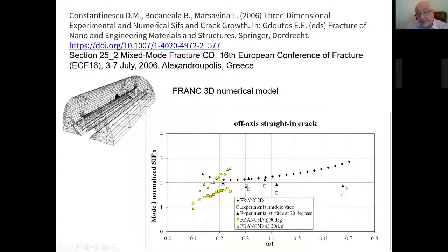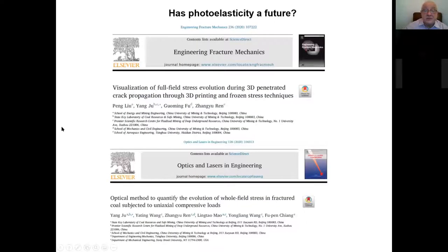Experimental results show that what is at the surface from the point of view of normalized stress intensity factor is a little bit greater than in the middle, and it slightly decreases, as I have mentioned previously, if the crack is grown more. We had this extreme experimental situation when we had this ratio 0.7, so the crack almost penetrated, and we had also situations for penetrated crack.